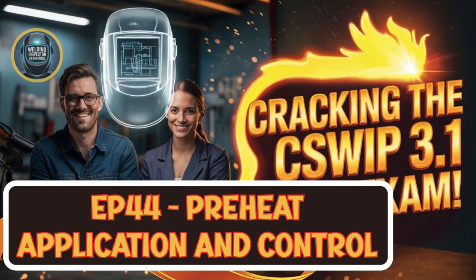Okay. Now, this level of detail about preheat, the specific temps, the measurement rules, it's fascinating, but why does all this meticulous control matter so much beyond just doing it right? What are the real-world consequences if someone cuts corners, maybe skips a preheat they thought was minor? It matters immensely. Because these temperatures, the preheat, the interpass temps, they aren't just suggestions pulled out of thin air. They're specifically calculated using established methods found in major industry standards. Like codes and specifications? Exactly. Your source mentions examples like BS EN 1011-2 from the British standards or AWS D1.1 from the American Welding Society.